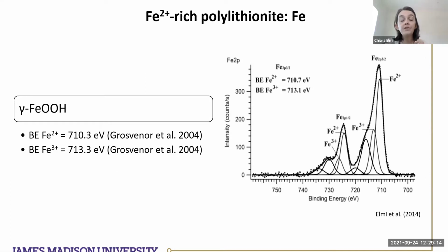I told you that the anion in the structure is not just oxygen, but you also have fluorine and OH. So based on the binding energy, it's possible to discriminate the valence state, but also understand if there's any clustering in the octahedral layer. Based on the binding energy of the 2+ and the 3+ iron, we noticed that the preference is with the OH. So we were able to notice that there's more organization than what was thought before. Before these studies, it was thought that there was a random orientation of the fluorine and OH in the apex of the octahedra, but it's more organized than thought.